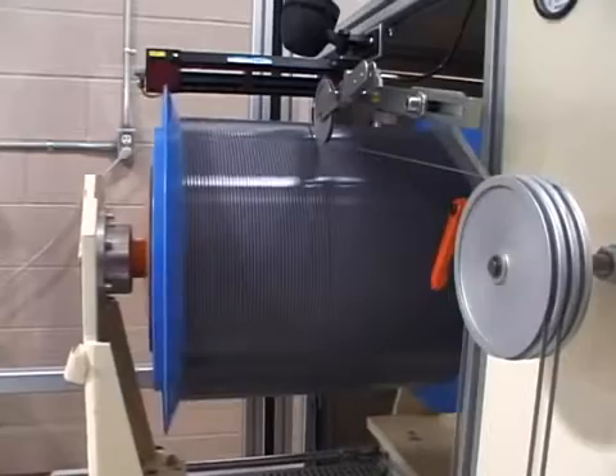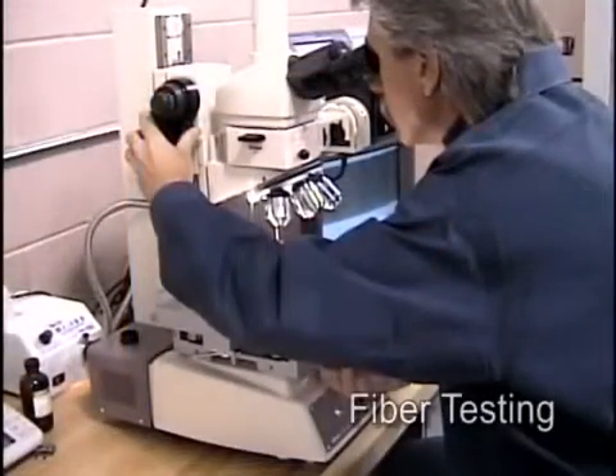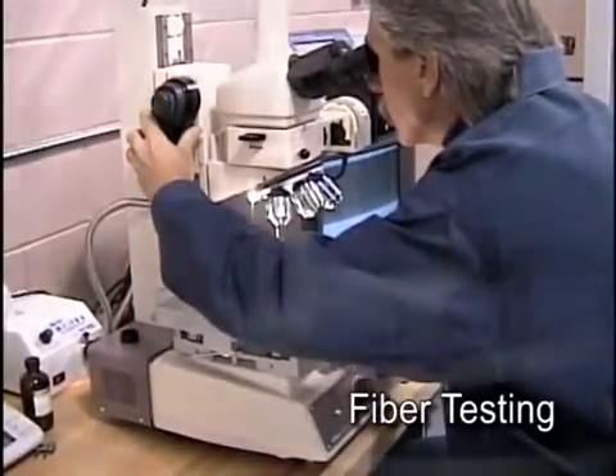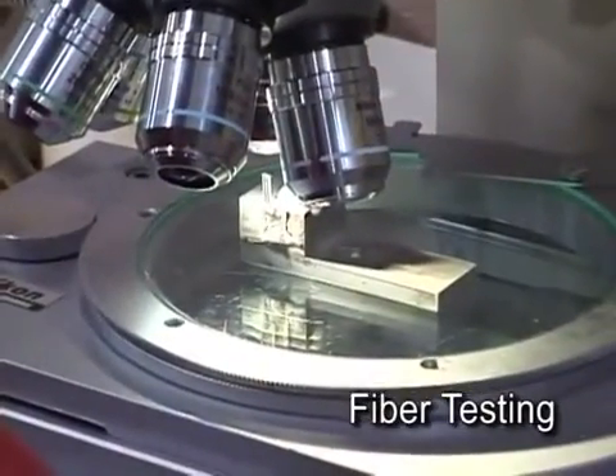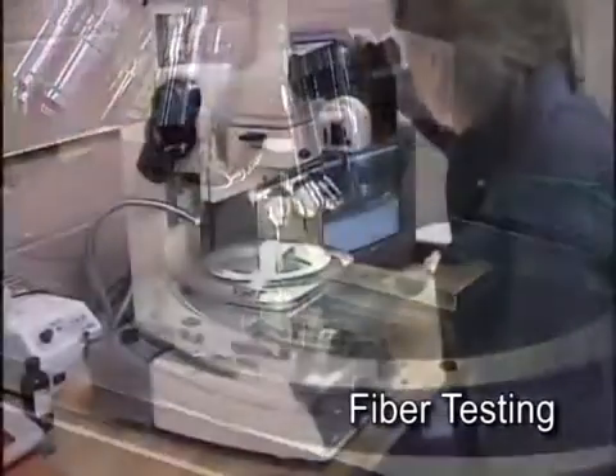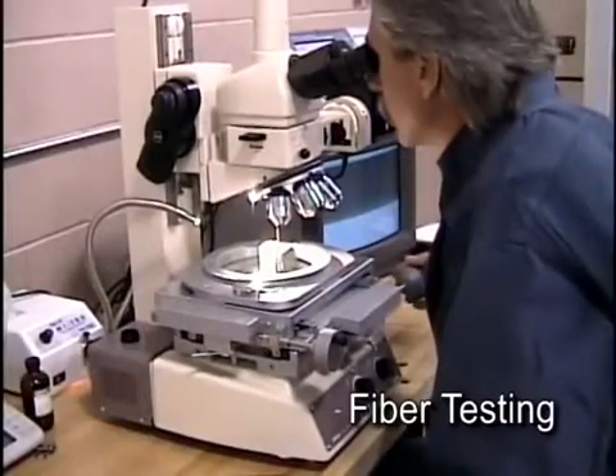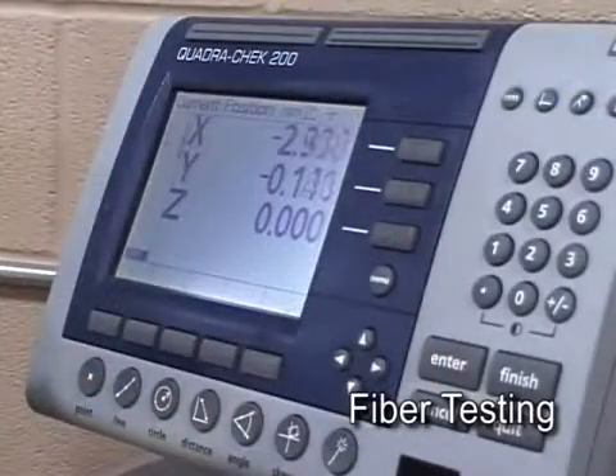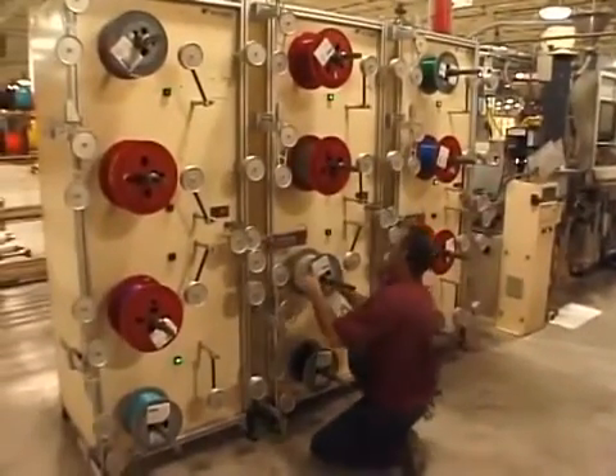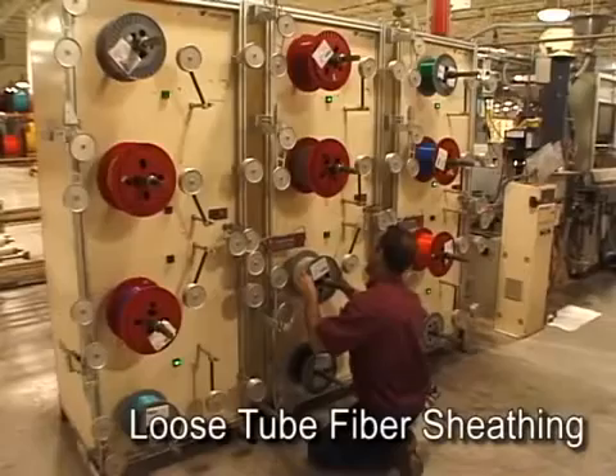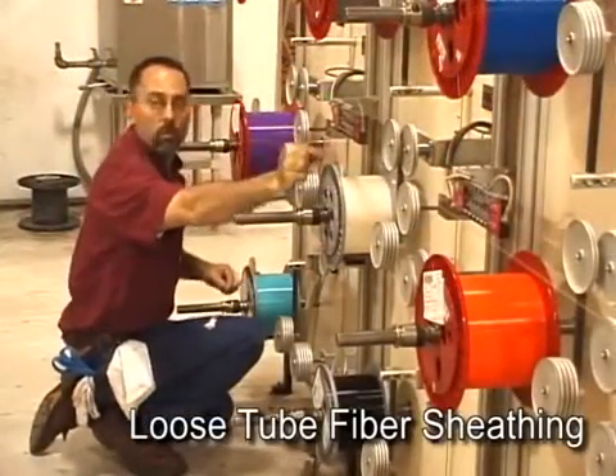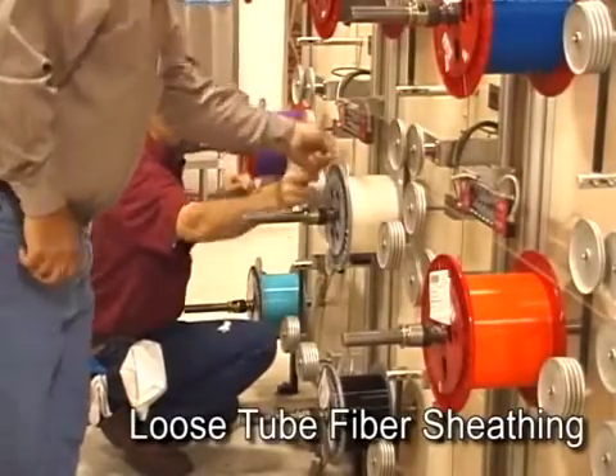Before the ribbon can be used in any cable, however, it must be tested to verify that its structure and dimensions meet specifications. A small length of ribbon is cut from the reel and placed under a microscope. A technician carefully examines the ribbon sample and fully documents the results. Only if the sample passes inspection can the reel go on to be used in a fiber optic cable. All three of the basic fiber cable designs, loose tube, ribbon fiber, and tight buffered cables, require some form of sheathing process. This is usually another intermediate step, but can be the final production step for small premises cable designs.